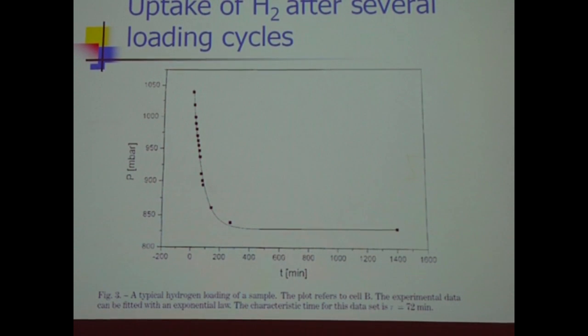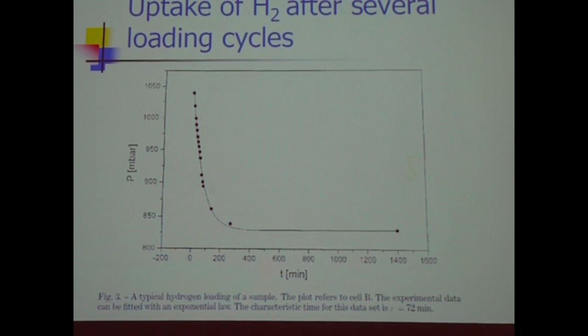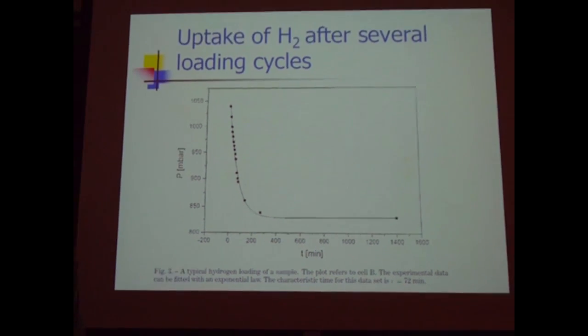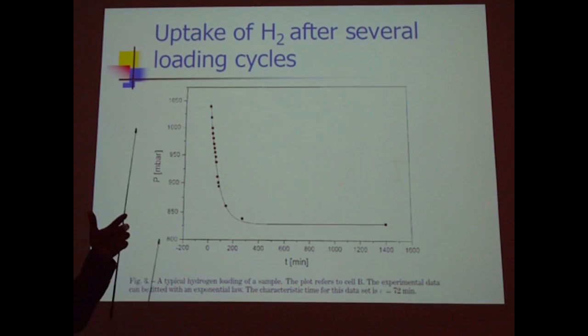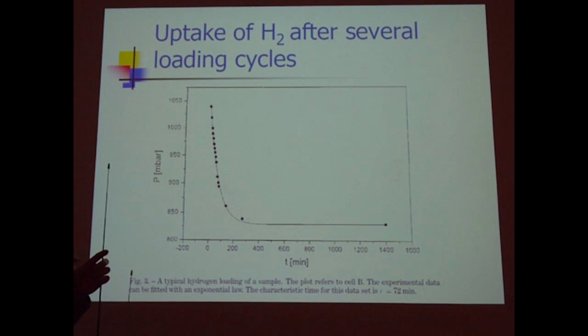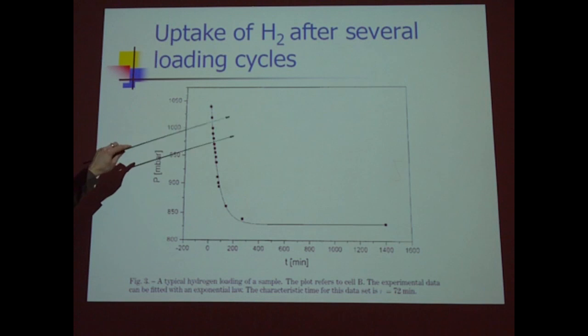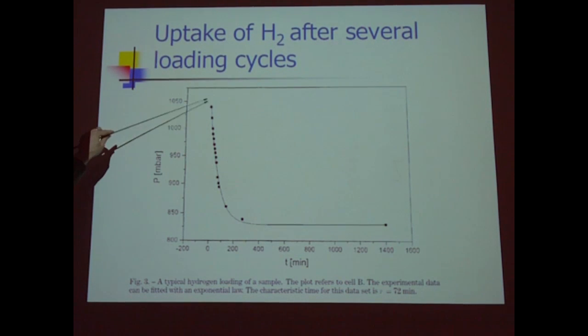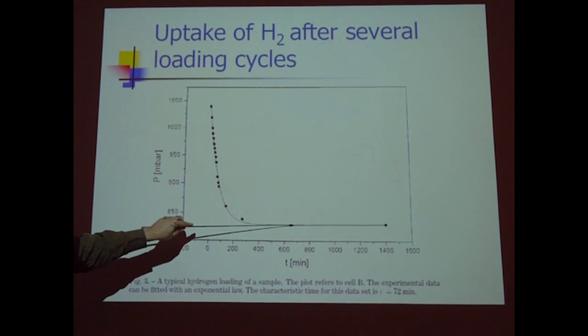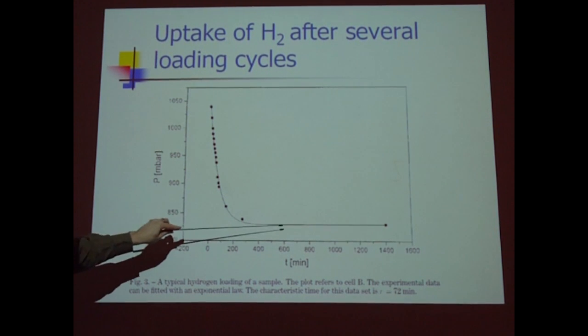On the other hand, if you look at their experimental data, a good way to figure out how much loading you have is to measure the hydrogen gas pressure in the cell. So for example, in experiments we did at MIT, we would load a volume up with hydrogen gas or deuterium gas, and heat the sample up to burn off the oxide layer. Once the oxide layer is burned off, then you get to see the pressure go down. It drops like a rock while the metal absorbs all the hydrogen and deuterium. Here we're seeing it going from over 1,000 mbar down to 830-ish mbar. So you're seeing the pressure going down.